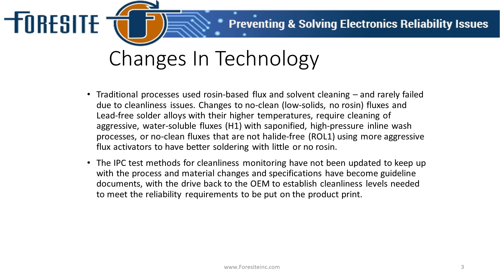The other issue is cleanliness monitoring. We've been using traditional tools for monitoring the cleanliness of a circuit board, which is just pouring some alcohol and water over the surface of an assembly or a bare board, and then measuring the resistivity change before and after. Using a very complex calculation and algorithm, we would come up with a function of: is this clean or dirty? But it never correlated to reliability or predictability of field performance. It was just a general gauge to say, was the system cleaning as well as it did before — using solvent systems with rosin fluxes.